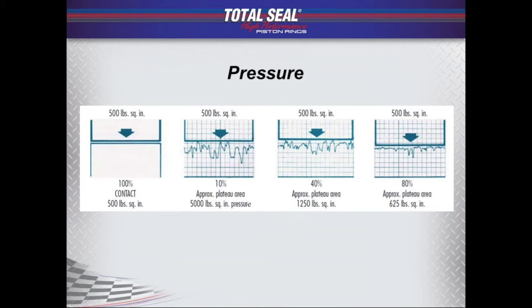And that's reduced the pressure on the ring from 5,000 pounds per square inch down to about 1,250 pounds per square inch. Again, less wear on the ring, less wear on the bore. We're ultimately going to achieve that plateau on the cylinder quicker, and we're going to have that ring seal come in faster.